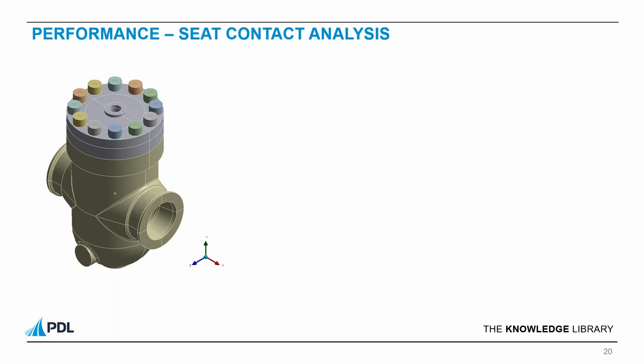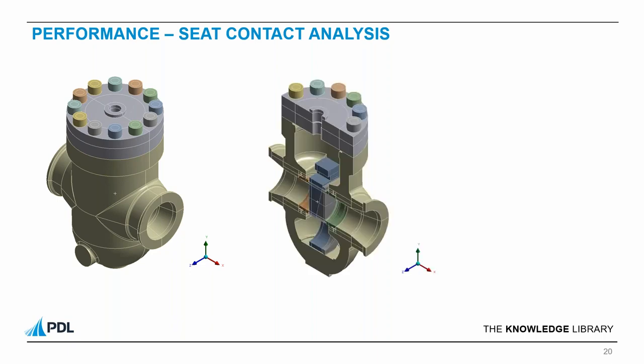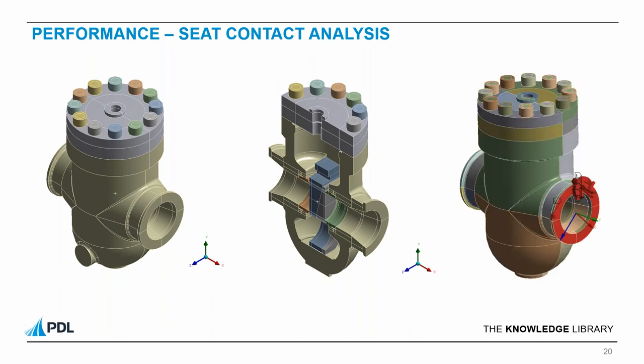So once your structural capacity has been determined, you may want to acknowledge the functional requirements. One example is this 12-inch split gate valve. You can see the split gate in there. Now, this valve has large bending moments and shear forces applied during operation. The valve will sit at a 45-degree angle, which is why we've got an offset loading coordinate system here. Sealing faces between the seat and the split gate required verification before a PO was placed.